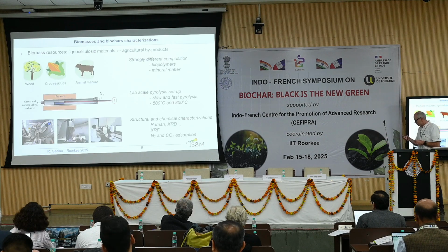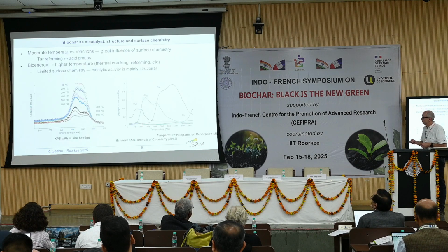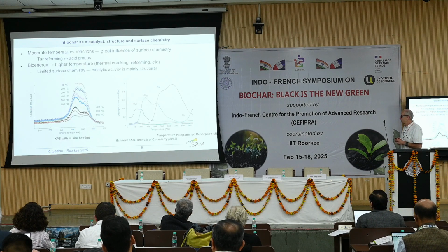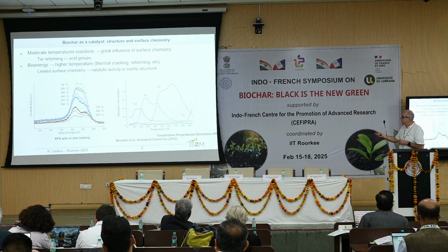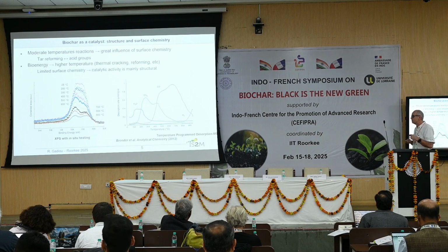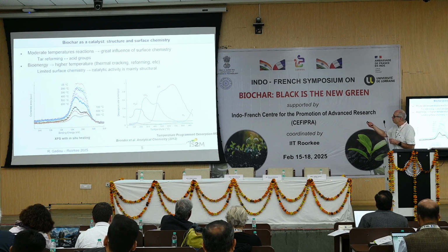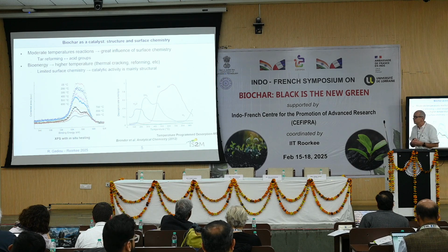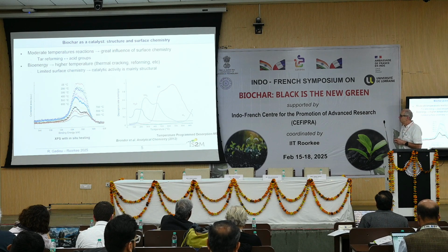So for this, the advantage to say about chemical analysis, it was shown that doing quantitative XPS is huge work. It's complex, but temperature programmed desorption gives a quantitative analysis if you are doing some good work, which allows you to follow very precisely the surface chemistry of the material. So you are able to do that, and it's very efficient and very reliable if you do some good work